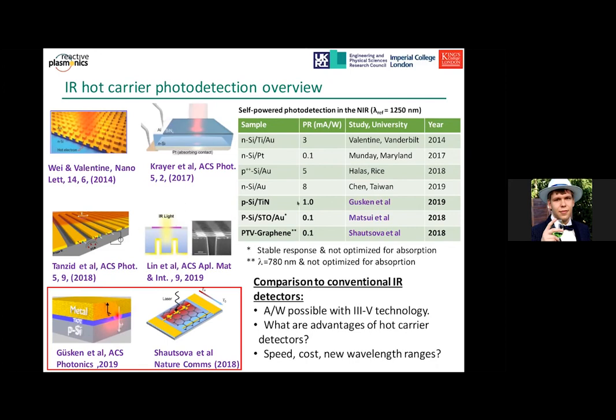For example, the titanium nitride silicon compound, which uses the native oxide layer for efficient harvesting of photoelectrons, the strontium titanate detector, and for example the photothermoelectric graphene detector. You can already see from this table that these detectors, even as a proof of principle demonstration, apart from offering additional unexplored geometries and material compositions, already allow sensitivity values approaching the state of the art, and they can be further improved.